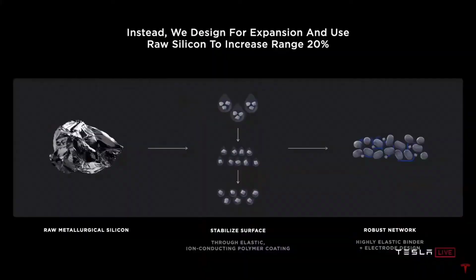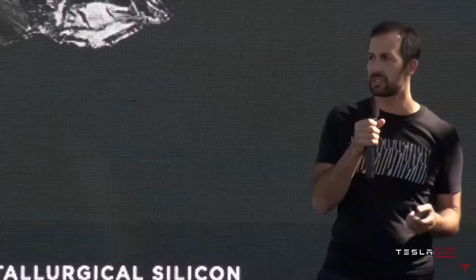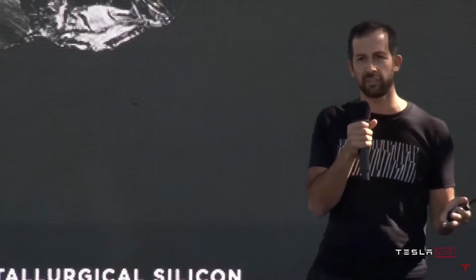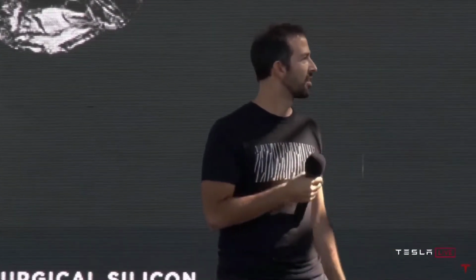And how does it work? Start with raw metallurgical silicon, stabilize the surface with an elastic ion conducting polymer coating that is applied through a very scalable approach. No chemical vapor deposition, no highly engineered high capex solutions, and then integrated into the electrode through a robust network formed out of a highly elastic binder. And in the end, by leveraging this silicon to its potential, we can increase the range of our vehicles by an additional 20%, just this improvement. Yeah, it gets cheaper and longer range.